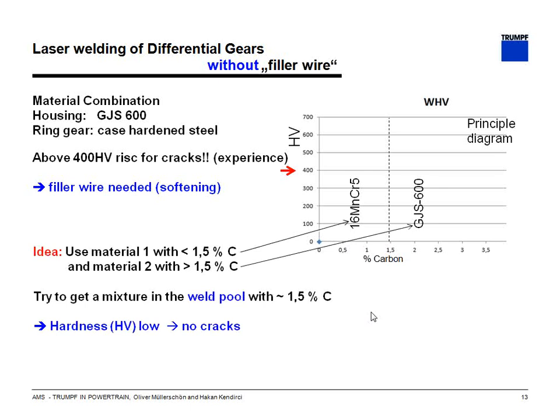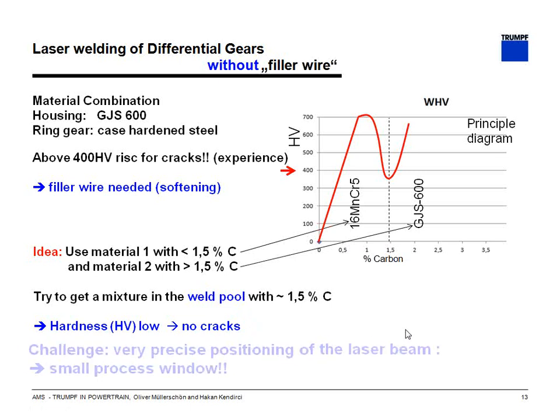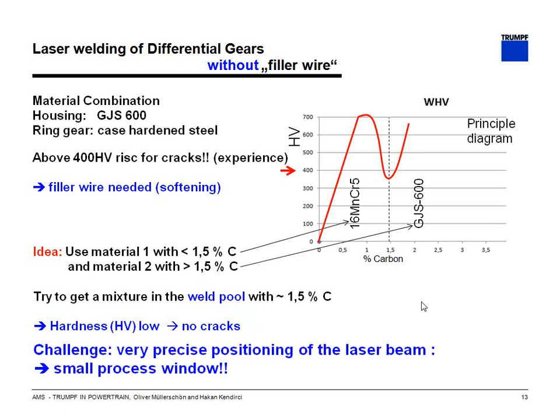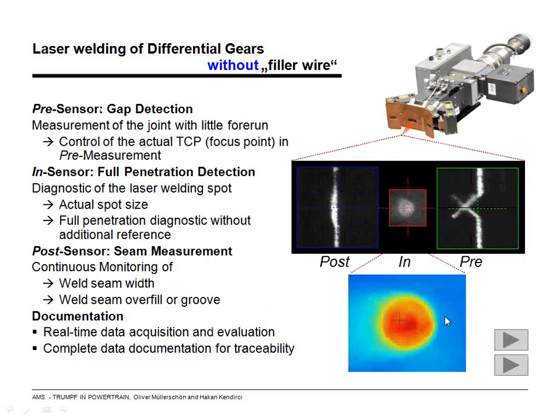But anyhow, there was the idea, what happens if we mix the materials here, material 1, for example, the cast material on the right side and the case hardened steel here on the left side. If we are able to mix it in the right way, there's a special thing with the hardness. If it's done in the right way, there is one position or one mixture, carbon mixture here, which allows us to weld the parts without any wire and to get a lower hardness. But the challenge is we need a very precise positioning of the laser beam, and it's still a small process window.